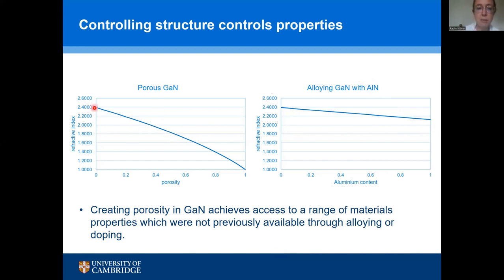Whereas if we think about the range of porosity we can introduce into gallium nitride, we can get a much, much broader change in refractive index. And we can achieve potentially materials properties that would not be accessible via the alloying route. We can get forms of gallium nitride which, because they are porous, show us properties we can't otherwise achieve.